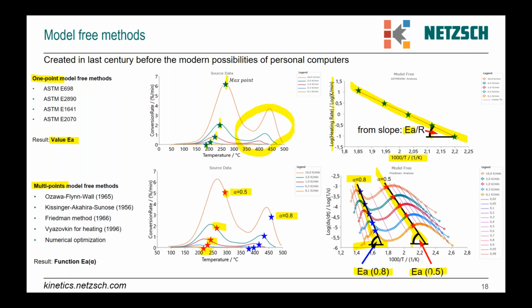So it means that the activation energy is different for any conversion. This could be done for any conversion value, and the result of this analysis is a function, activation energy as a function of conversion. What's good? Again, it's fast. What's bad? For each point, only one value of activation energy is found.